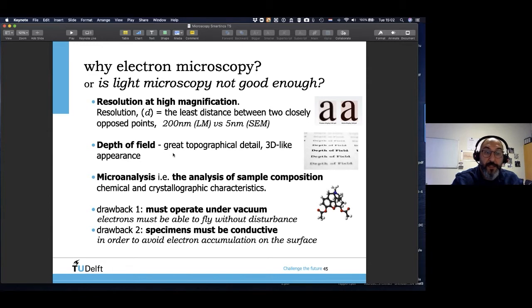So drawback 2 is the specimens must be conductive. Again, if you are using very high vacuum, you are sending your electrons on top of your specimen, and those electrons should eventually go somewhere. If they don't, if they accumulate, then the next coming electrons will not be able to reach the specimen surface and they will be deflected, right? Minus rejects minus. So this is a problem, of course. That's the reason we are using coatings like carbon coatings or gold coatings, depending again on your application, in order to let the electrons dive into our specimen, do their job, and go away.